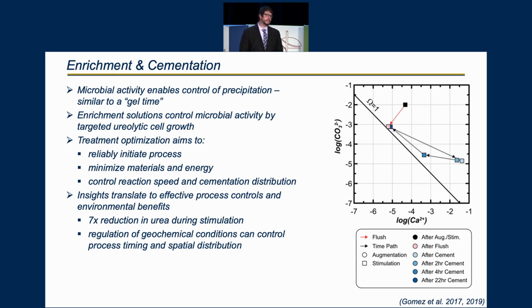A subsequent cementation injection is then applied and pushes the system out to higher calcium activities. It is then ureolysis that continues to generate carbonate hours after injections, therefore consuming supplied calcium until near equilibrium conditions are achieved between the fluid and mineral phases, and only then does the system become ready for a subsequent treatment injection if it is desired.